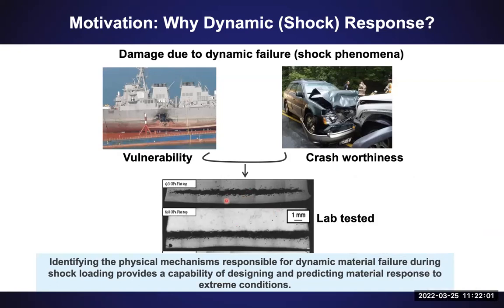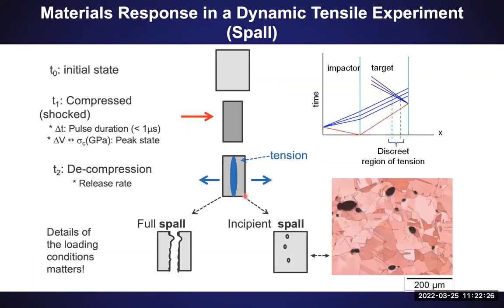So here, on the bottom of this slide deck, are some micrographs of materials that were impacted with dynamic loading. And you can see in the center of the material, there's a region that opened up. So we try to basically understand how our loading condition leads to the amount of damage that happens in materials. How do we actually do that? And what is dynamic loading?